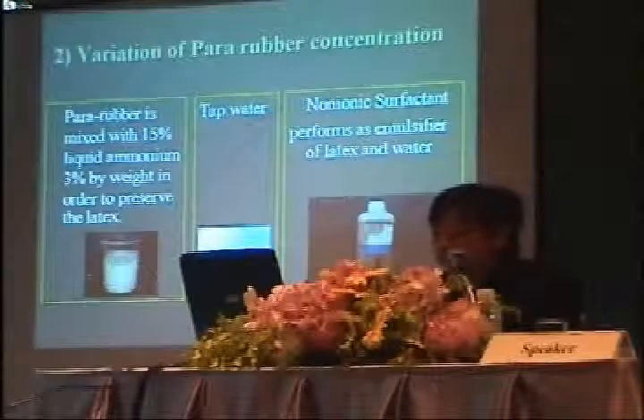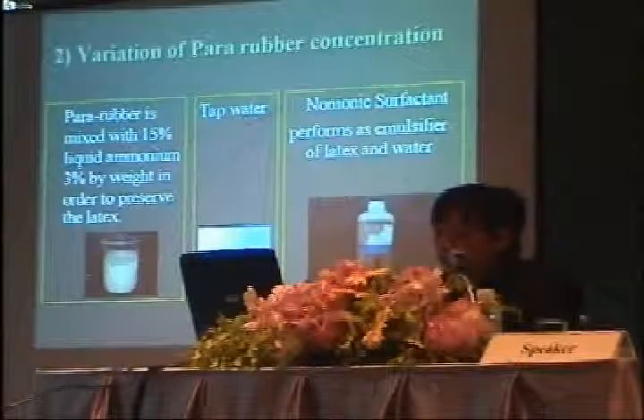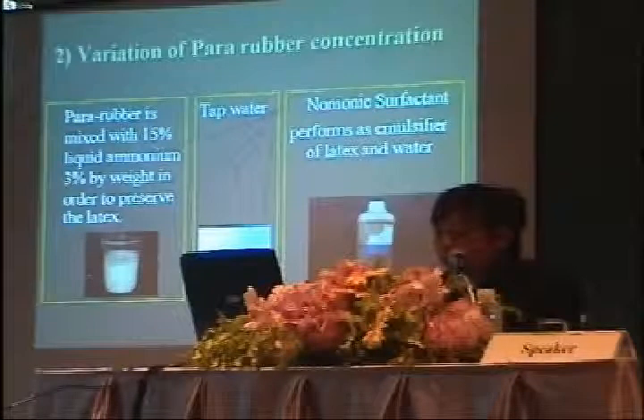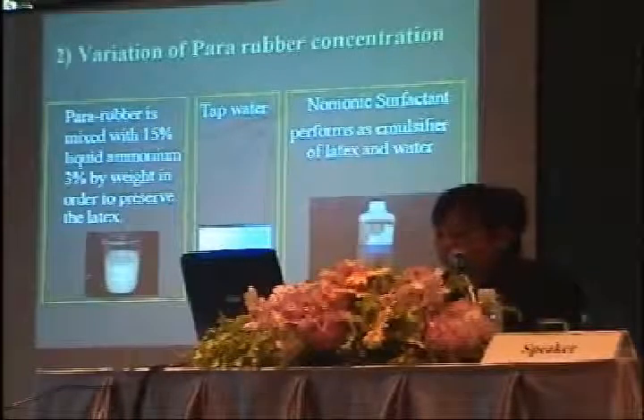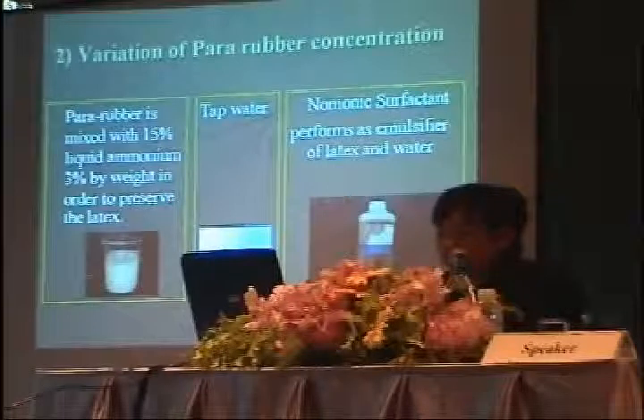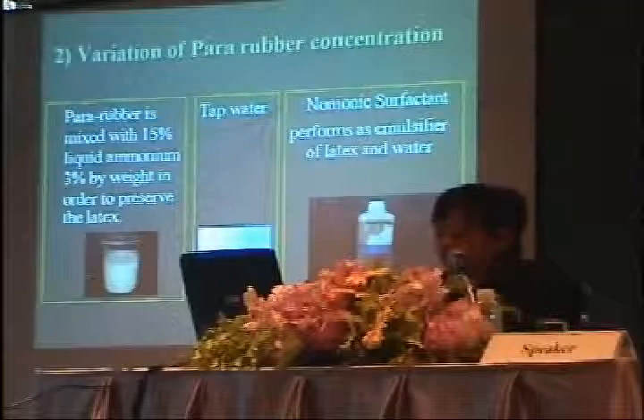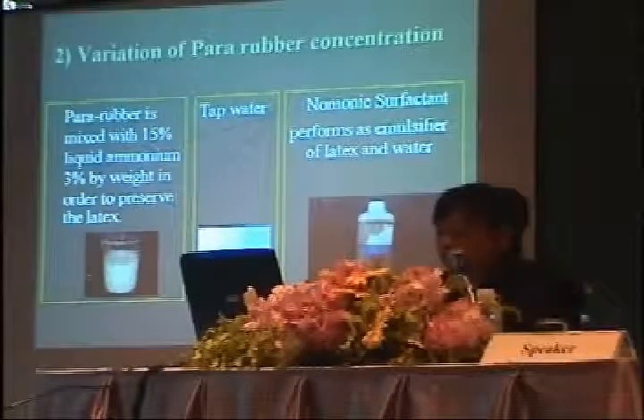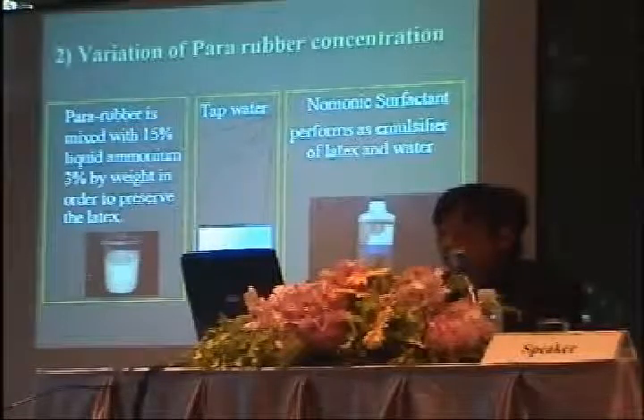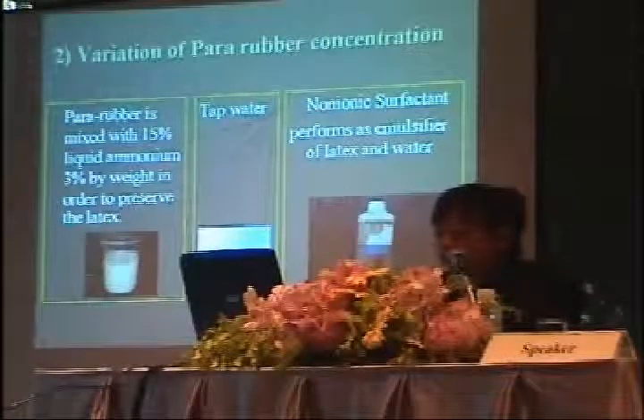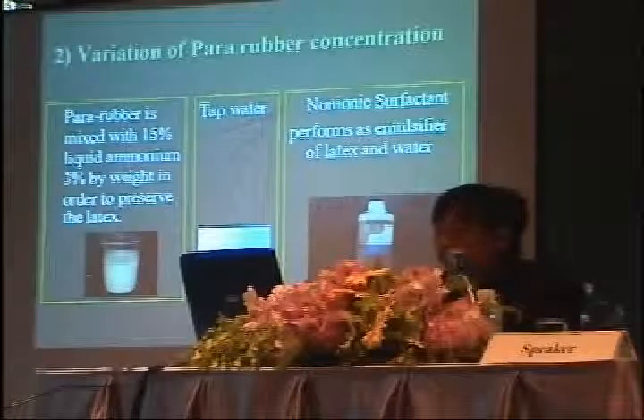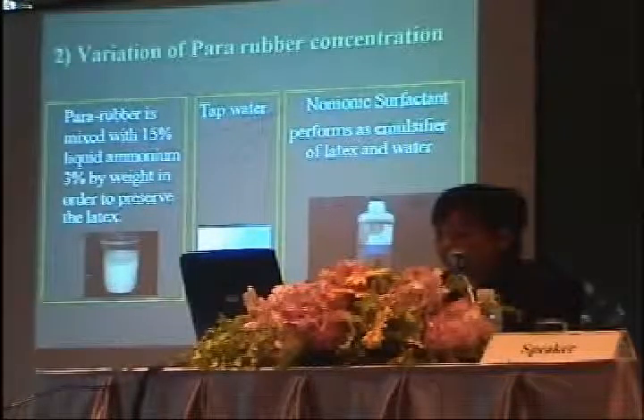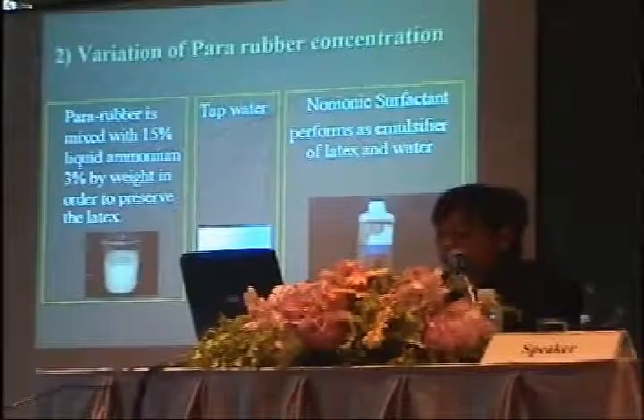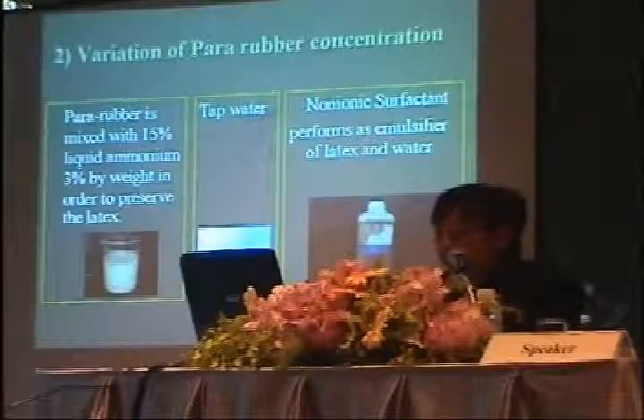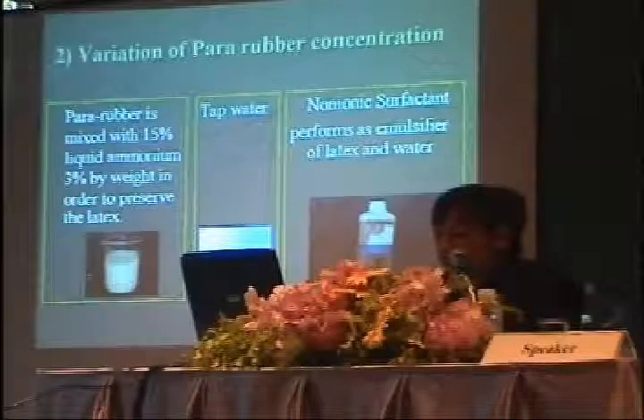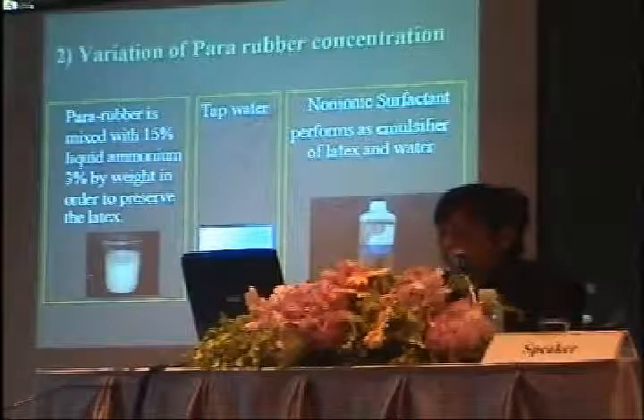The second experiment is finding the coefficient of thermal conductivity when varying the para rubber concentration. Para rubber is mixed with 15% liquid ammonia 3% by weight in order to preserve the latex, and then tap water and non-ionic surfactant are added. Non-ionic surfactant performs as an emulsifier of latex and water.